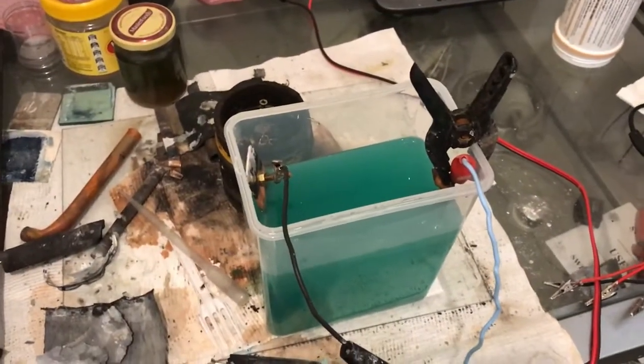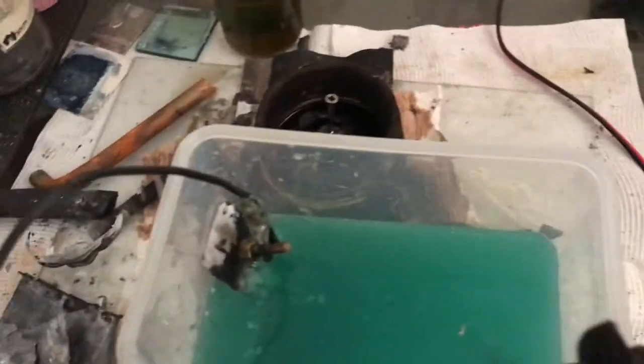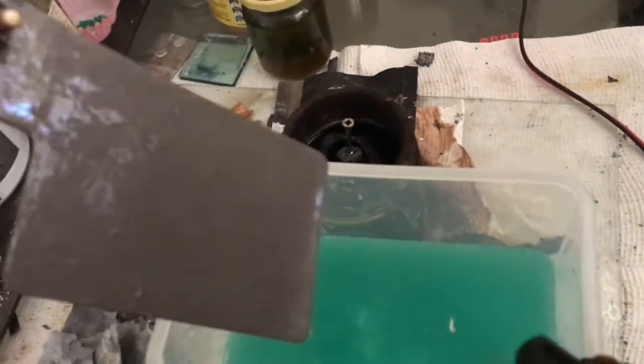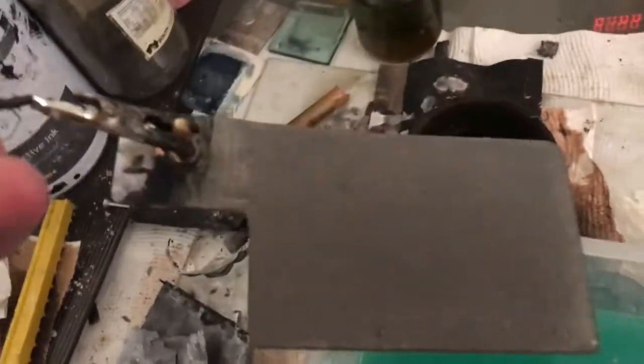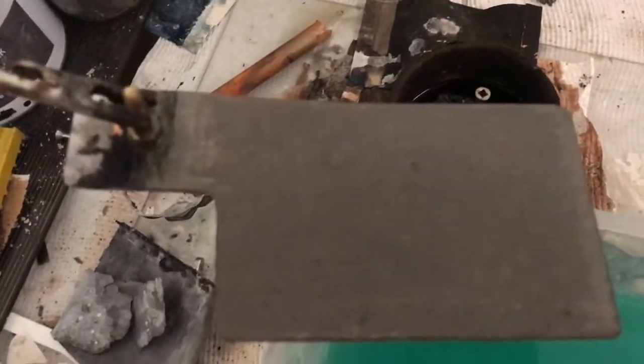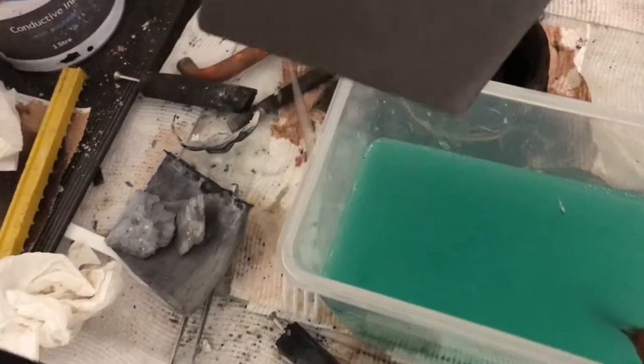Alright, we'll get back. 3 hours later. Okay, we have a successful plating of nickel on both sides. I did 1.5 hours on each side. Those marks you see there are just the grinding marks I put in the carbon to increase the grip into the plastic before coating it with the